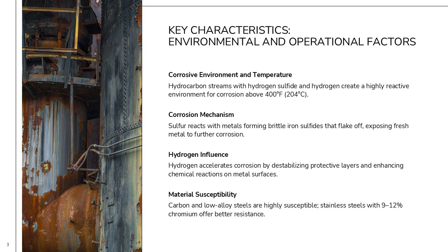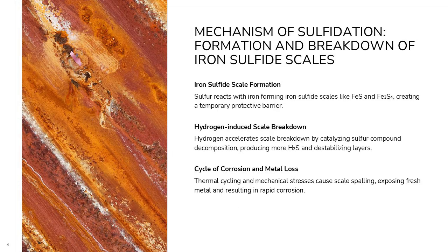The mechanism of high-temperature H₂S or H₂ corrosion involves a series of chemical reactions between sulfur compounds and metal surfaces. Initially, sulfur reacts with iron to form iron sulfide scales, such as FeS and Fe3S4. These scales act as a temporary barrier, slowing down further corrosion. However, the presence of hydrogen significantly accelerates the breakdown of these scales. Hydrogen promotes the catalytic decomposition of sulfur compounds, increasing the formation of H₂S and destabilizing the sulfide layer. As the scales become brittle, they spall off due to thermal cycling and mechanical stresses, exposing fresh metal to corrosive agents. This continuous cycle of scale formation and spalling leads to rapid and uniform metal loss.